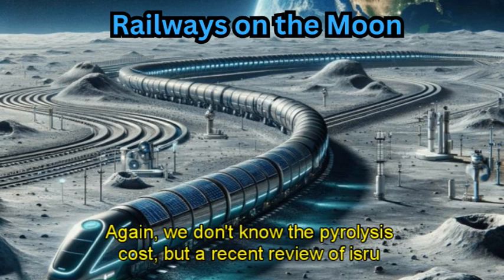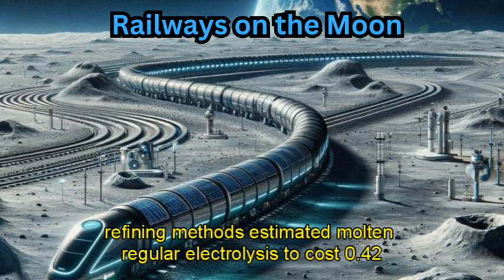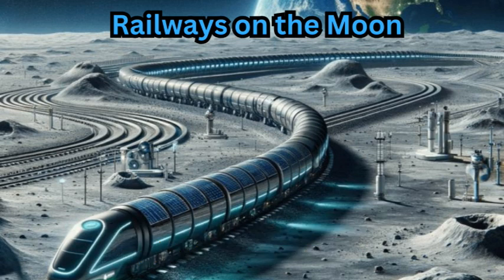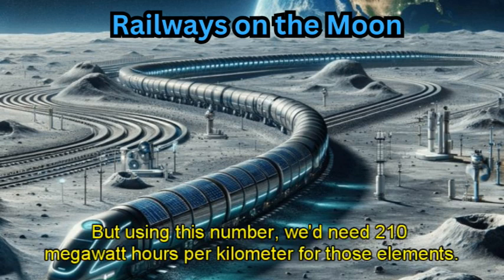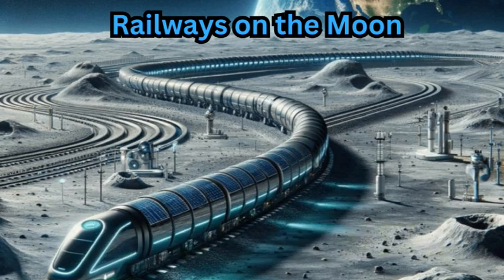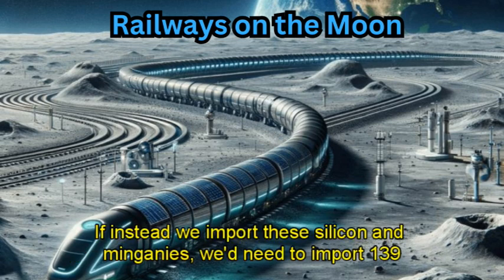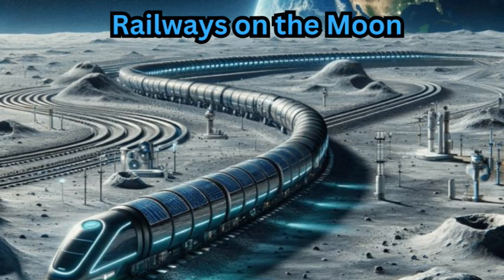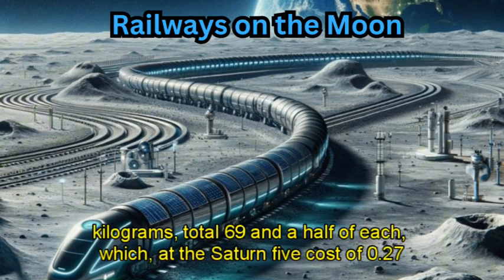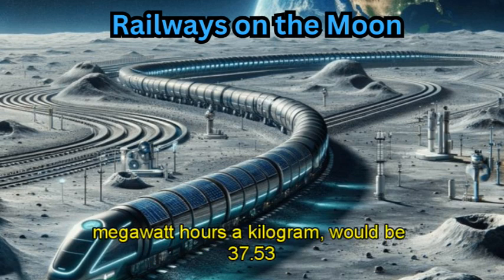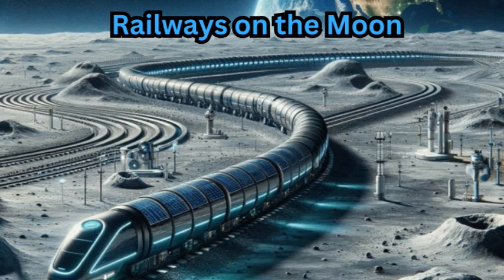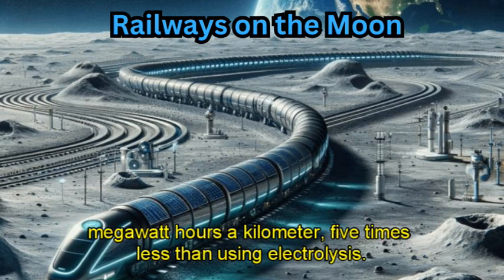Again, we don't know the pyrolysis cost, but a recent review of ISRU refining methods estimated molten regolith electrolysis to cost 0.42 megawatt hours a kilogram. Likely it will be higher, but using this number, we'd need 210 megawatt hours per kilometer for those elements. If instead we import the silicon and manganese, we'd need to import 139 kilograms total, 69.5 of each, which at the Saturn V cost of 0.27 megawatt hours a kilogram would be 37.53 megawatt hours a kilometer,